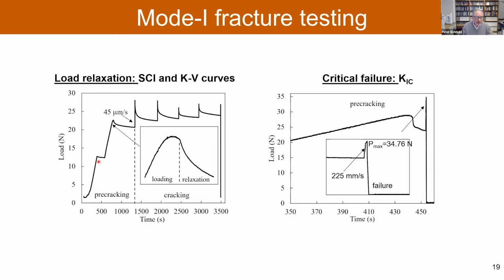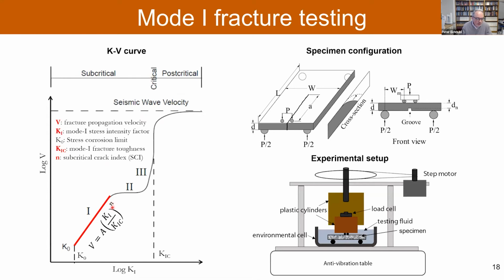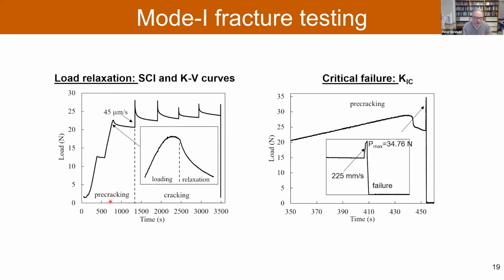The other test is where we load the sample a little bit at a slower rate, repeatedly, until the crack propagates. Then we release the stress and let the crack decay, and then another loading cycle and decay, and another loading cycle and decay. So with repeated tests, the load decay rate gives us a measure of the subcritical fracture behavior, which is called the subcritical index. It's the slope in this plot here. So this exponent here is called the subcritical index. That's what we measure with those repeated load decay cycles, and that is one way to quantify this subcritical fracture behavior as a function of chemical environment.